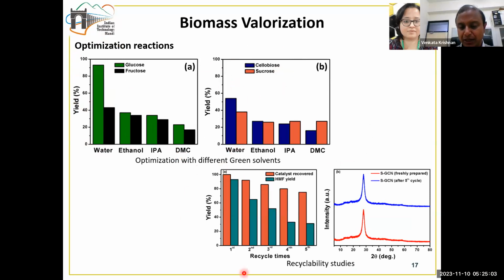Subsequently, we did the recyclability of the reaction, wherein we recovered the catalyst after each cycle and then recycled it. We found that although the HMF is forming during the reaction, there are some changes in the yield. These yield changes are due to a compound called humins, which is formed during the process. These humins block the catalytic active sites during the reaction, which leads to the decrease in the yield. We were able to figure out the reason for this decrease.